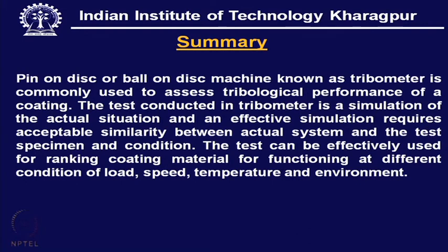So, this way we can look into the various aspects of tribometry, that means the science and engineering of measuring the coefficient of friction and the resistance to wear of the coating. For a particular coating the behavior can vary depending upon the structure of the coating, its crystallographic orientation, and sometimes the coating is also sensitive to humidity. A coating that works excellently, with remarkable performance under high vacuum, can show very poor performance in a humid atmosphere.